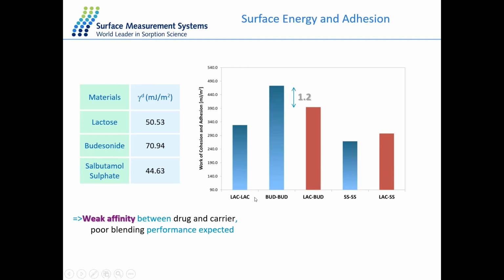So if we want to look at the blending for the lactose and budesonide, what we can first look at is the lactose cohesive properties of itself and the budesonide cohesive properties of itself. What we can see when we compare these two is that budesonide has a stronger affinity to interact with itself, and this will cause higher aggregation compared to our lactose and lactose. So in this case, we would have a weak affinity between the drug and the carrier, and we would expect quite poor blending performance.